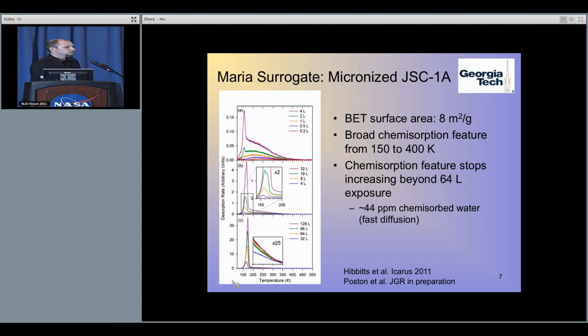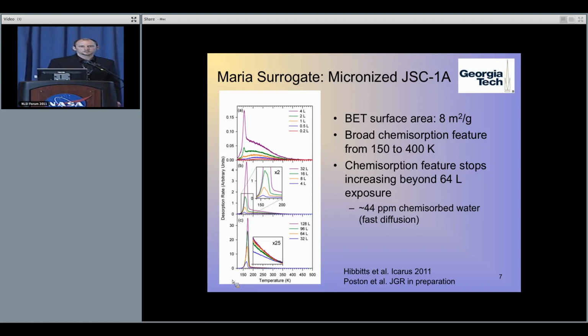But we do see other features. This narrow feature over at about 150 Kelvin, we believe is ice, water ice, of course. And then this feature over here could be one of two things. It could be ice that's bouncing around within our powder matrix and then trickling out over time, over a range of temperatures, or it could be a distribution of these molecular chemisorption sites.